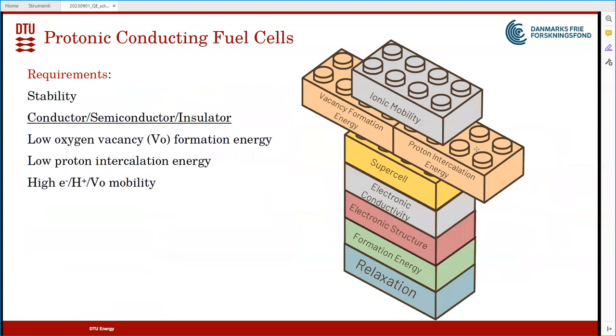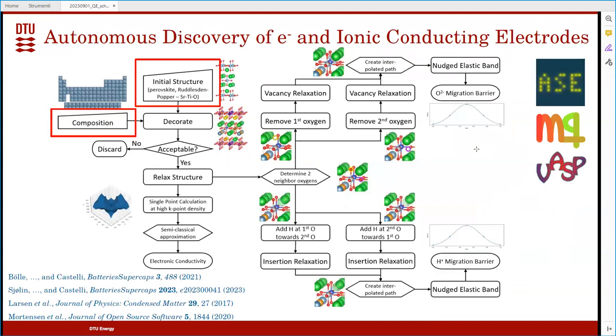So what we do is, again, we take the Lego bricks, and now we actually add, we already have the oxygen vacancy formation energy, if you remember, for the lithium or magnesium, but now we have also the proton intercalation energy. So we have the same structure of the workflow up to here. And then instead of adding lithium or taking out lithium, we have protons. And again, this is done all in the same way. Basically, it's my students that do this, and they use the same workflow. So you can see this is the logic behind it.